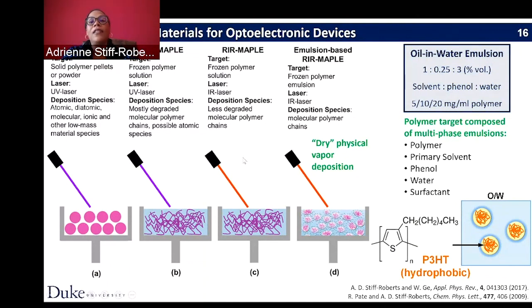So people then demonstrated resonant infrared matrix-assisted pulse laser evaporation. And in this case, you change from the UV laser to an infrared laser. So the first demonstrations used a free electron laser because it's a tunable laser. It can give you tunable wavelengths in the infrared. The problem with the free electron laser is that it's the size of a building, so it's not very practical for use in a system. But the idea, though, is that you have this tunable infrared laser. You have your same polymer dissolved in a matrix, which is the solvent, and you can then tune the infrared laser to a vibrational mode of a bond that's present in either the solvent or the polymer if you wanted to. And you then have resonant absorption of this laser energy. And because it's an infrared laser that's much lower energy, you can protect the polymer material.